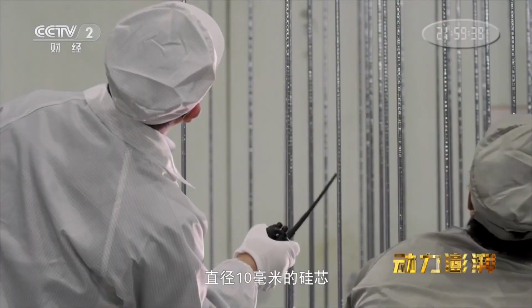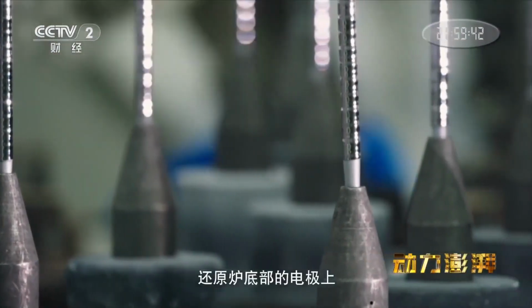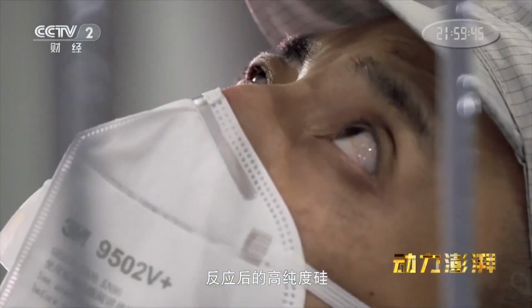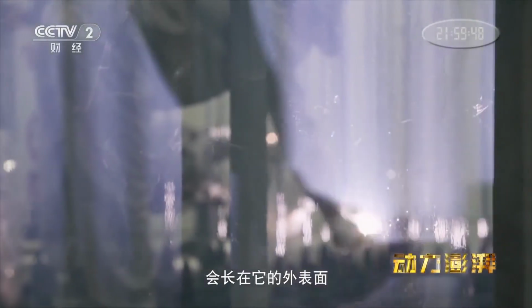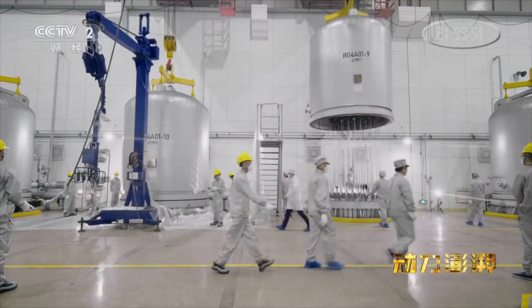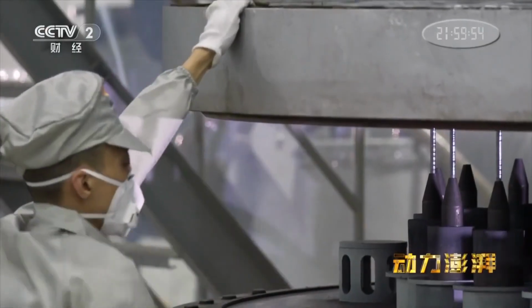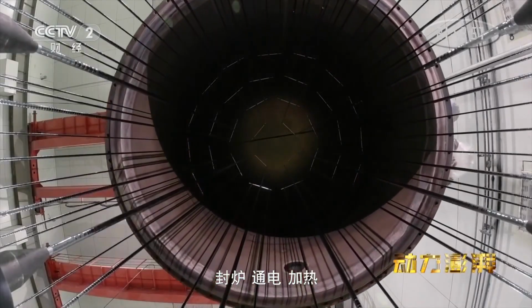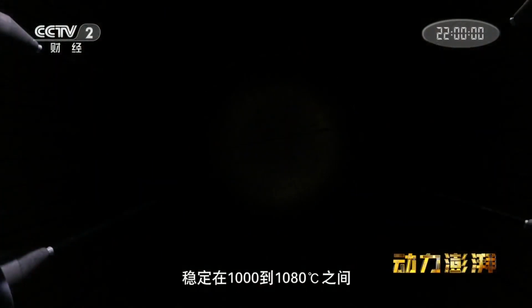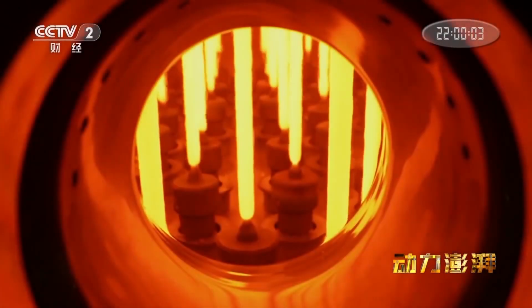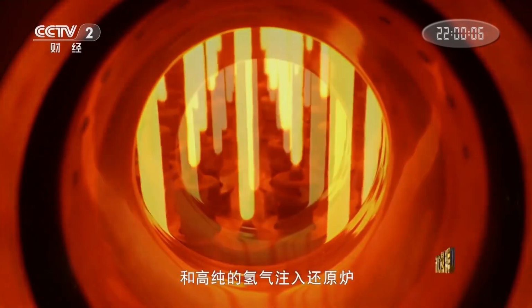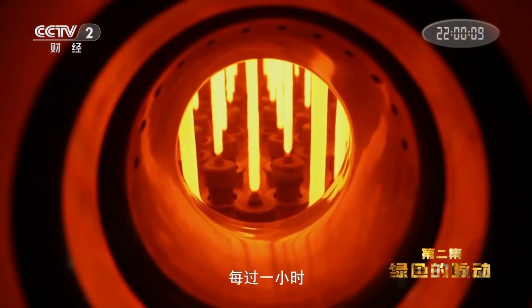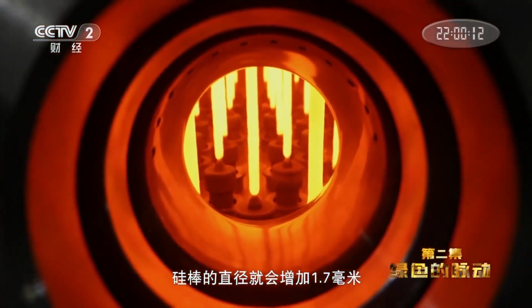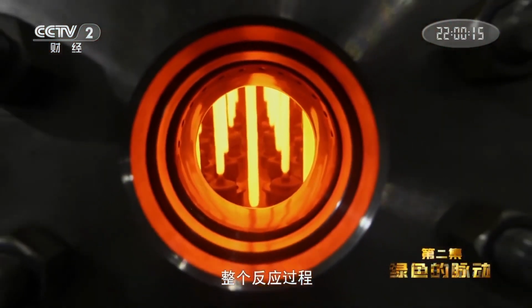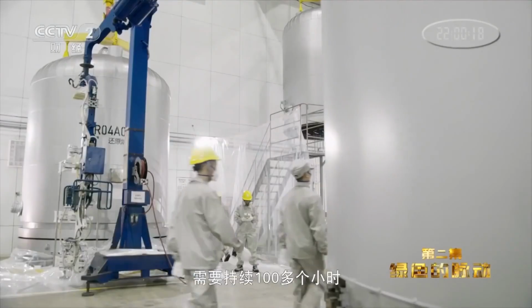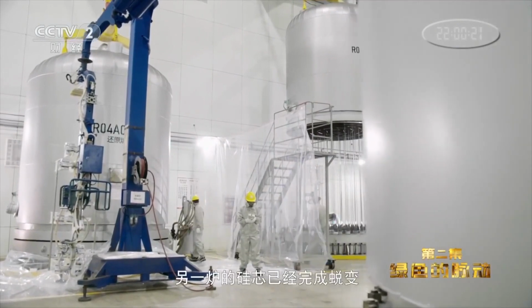Silicon cores with a diameter of 10 mm were sequentially mounted on electrodes at the bottom of the furnace. The reacted high-purity silicon will grow on its outer surface. After the furnace is closed, energized and heated, the temperature inside the furnace is stable between 1000 and 1080 degrees Celsius. Gaseous trichlorosilane and high-purity hydrogen are injected into the furnace. The diameter of the silicon rod increases by 1.7 mm every hour. The entire reaction process takes more than 100 hours. At this time, the silicon core of another furnace has been transformed.